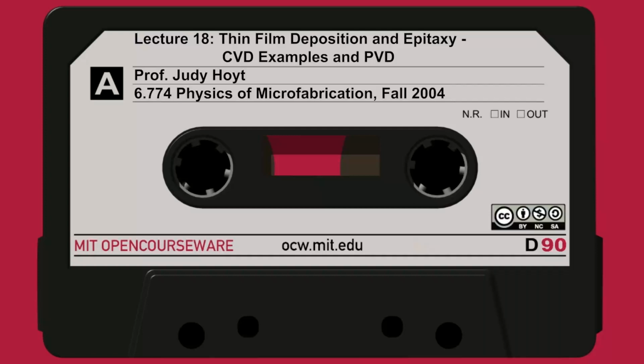So what are some common PVD films and how are they put down? That's listed on this chart I took from your text here on slide 30. Aluminum is put down in a number of different ways, but sputter deposition is really the most common. The standard deposition of aluminum is to hold the wafers pretty close to room temperature. There are some special sputter deposition systems where we'll put it down at about 400 to 500. So in other words, hot aluminum, and this is if you need to reflow the aluminum for better step coverage.